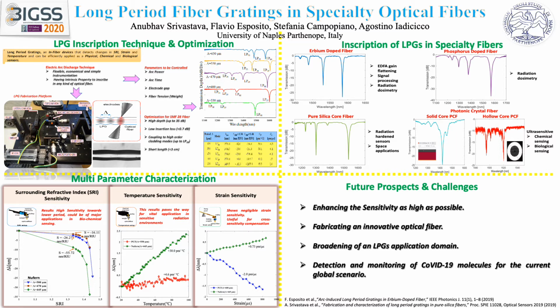So the whole setup was designed to permit the fabrication of gratings without creating any bending in the fiber during the process. The electrodes are electrically connected to a high voltage supply provided by commercial fusion splicers. You can see here the wire coming from the splicer to the holders, to the electrodes. The selection of the power and duration of the electrode supply current, as well as the axial tension of the fiber, allows the control of the modulation strength and thus the LPG spectral features, which is the most important aspect of getting a very good transmission spectrum, as you can see here in the inset, transmission spectrum versus wavelength.